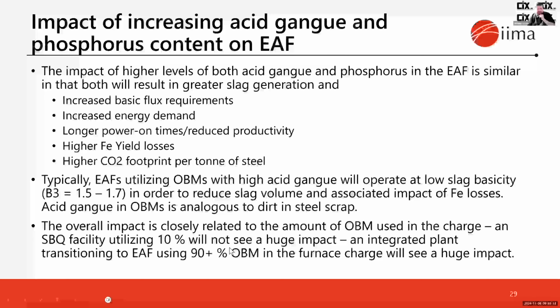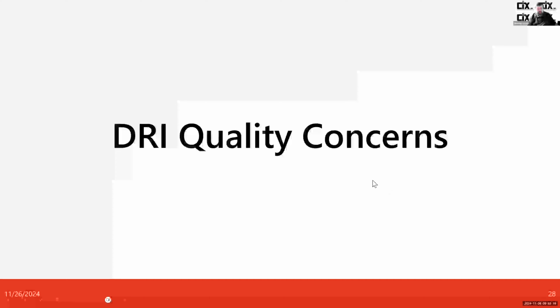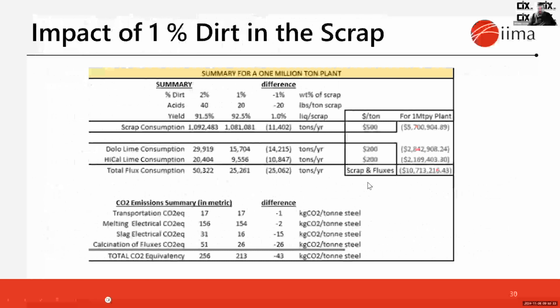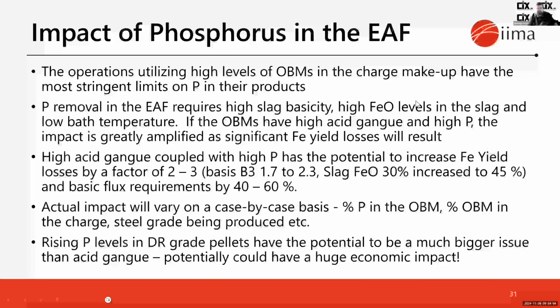The impact of things like gangue and phosphorus will be much higher on these integrated operations that are transitioning because of the quantity that they're utilizing. Just to give you an idea of the impact of an additional 1% gangue or 1% dirt in the scrap, this is a summary we generated within CIX for a 1 million ton a year plant. What we found is that the cost is about $11 per ton, and the impact on the CO2 footprint is an additional 43 kilos per ton of steel produced. So dirt content and gangue content are really important.